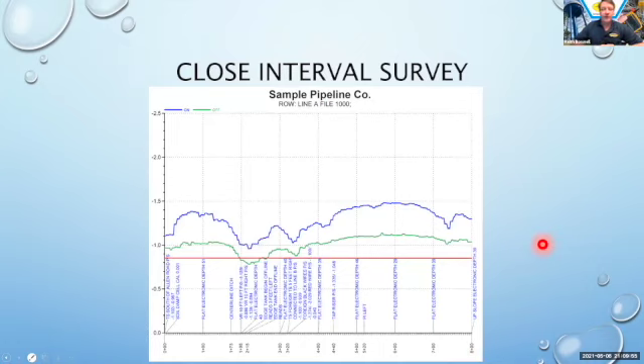This here is an example of a close interval survey. It shows, between your test points, where it's a discrete location that you're taking a reading, a close interval survey, like I said before, gives you a profile of what those readings look like between your different test points. In this example, we're looking at 800 feet of profile. The blue is our on potential. The green is that instant off or that polarized potential. And then this red line is that 0.85 criteria. So any areas where that off potential is less negative than 0.85 tells us that we're not meeting that criteria and we may be unprotected at that location. Without doing further testing, where you could do a depolarized survey across there to see if you have 100 millivolts polarization, that's our threshold. That's what we're looking for.